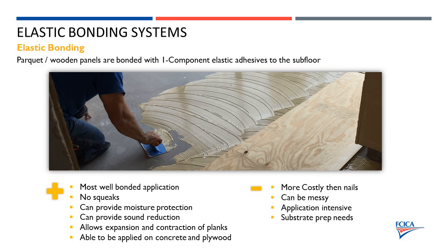But it also does cause some issues with pre-finished hardwood. So I talked earlier about how installers like to use adhesives with a fast cure rate if they're putting down unfinished hardwood. But if you're putting down finished, this type of a scenario can create some issues if that urethane gets on the surface of the finished hardwood. It can etch or ghost the surface, even if you clean it up and the adhesive is no longer visibly there. The haze of it or the ghosting of it that has affected the finish stays behind. So that can cause some issues. Guys have to go out and replace some boards sometimes if they've left adhesive on it too long.